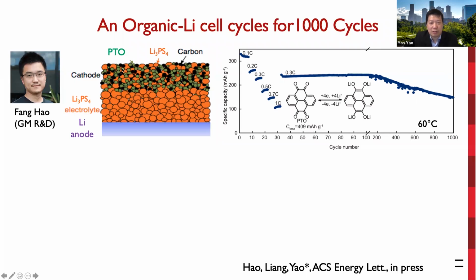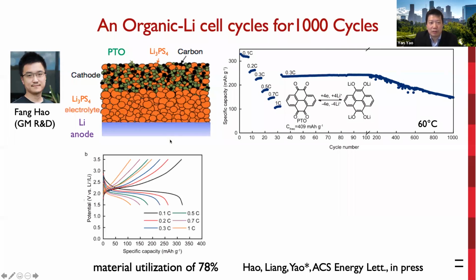The cathode composite was prepared by mixing PTO, LPS electrolyte, and carbon with a pestle and mortar, followed by uniaxial powder compaction. The PTO-lithium cell exhibits a discharge voltage of about 2.2 volts with a specific capacity of about 320 milliamp hour per gram, corresponding to a material utilization of 78%. The cell cycles stably at 0.3 C for the initial 200 cycles and maintains 61% of its maximum capacity over 1,000 cycles. This is truly remarkable capacity and stability for new cathode materials in solid-state batteries, which have been studied only recently.